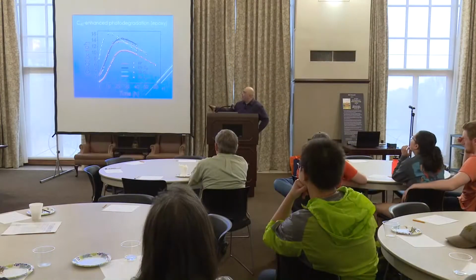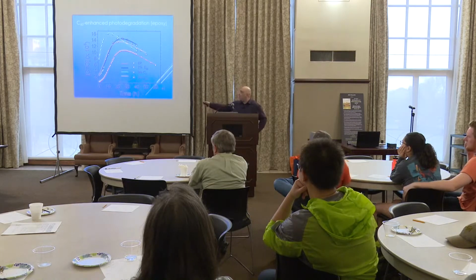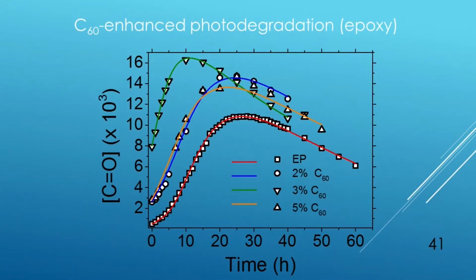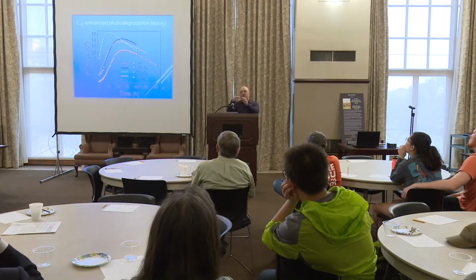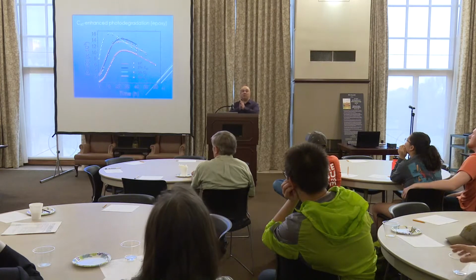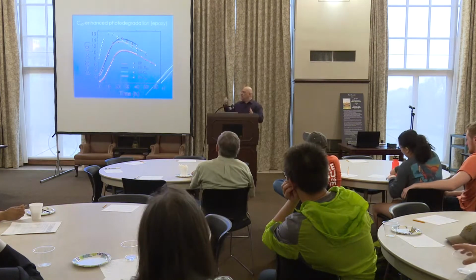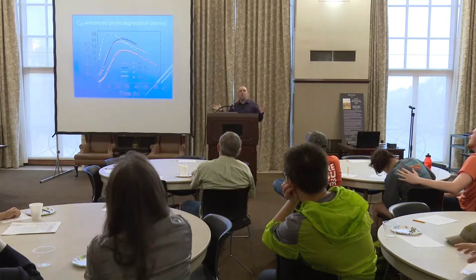Okay, so we said, let's put this in our plastics, and this red curve is without the Bucky Balls, the C60 molecules, but look at that green one. It's only 3% Bucky Ball, and the photodegradation is actually much faster. Actually, photodegradation even started during the making of this film, okay? But if you look at the 5% Bucky Ball density, we see a decrease in the rate, because when Bucky Balls come together, they try to de-excite themselves, which is called triplet annihilation. So the Bucky Balls were actually something to prove this model.